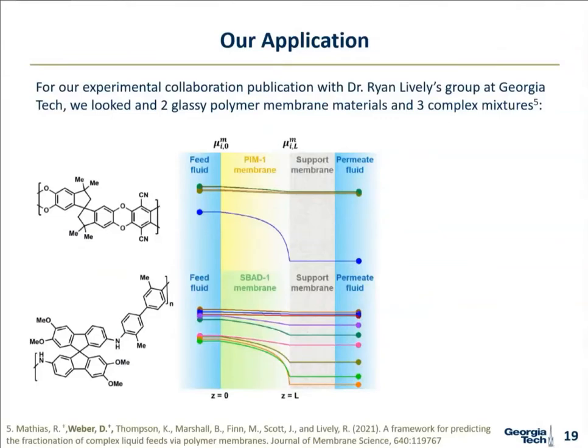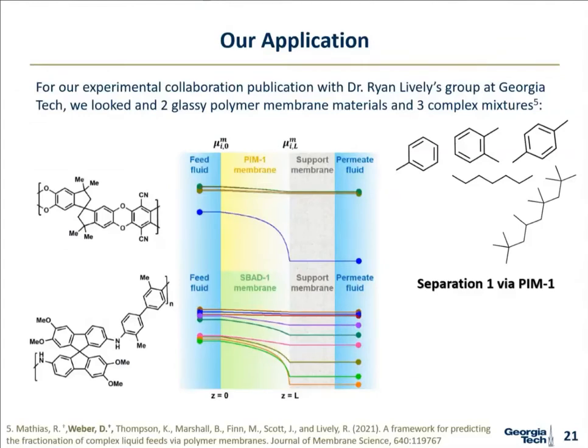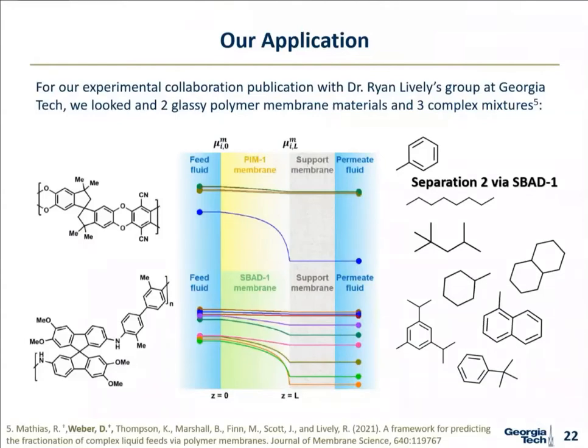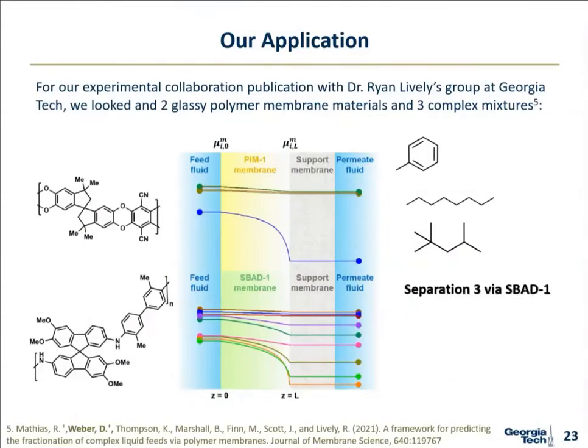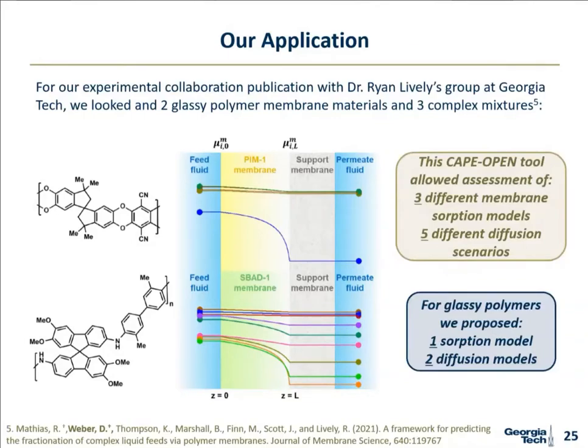For our specific application, through a collaboration with Dr. Lively's group at Georgia Tech, we looked at two different glassy polymer membranes and three different complex mixtures — a variety of 12 different organic molecules. Separation one was a five-component mixture through PIM-1; separation two was a nine-component separation through SBAD-1; and separation three was another very complex mixture through SBAD-1. This CAPE-OPEN tool enabled us to assess three different membrane absorption models and five different diffusion scenarios. We also proposed a new sorption model and two novel diffusion models for glassy polymers.